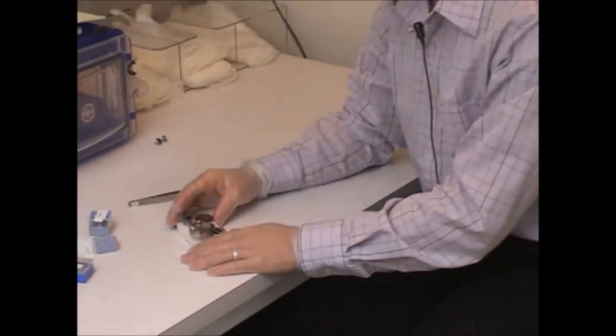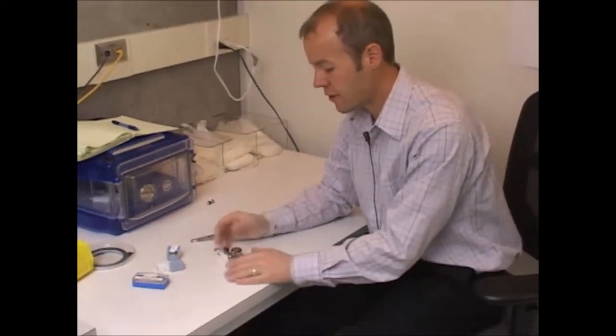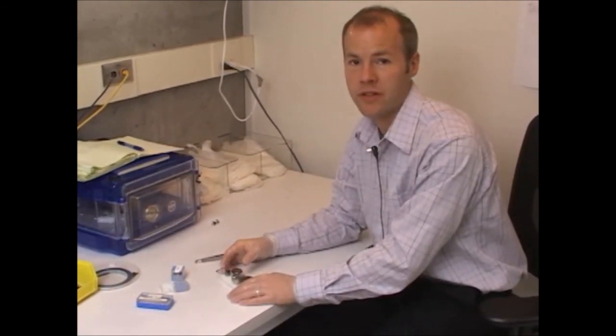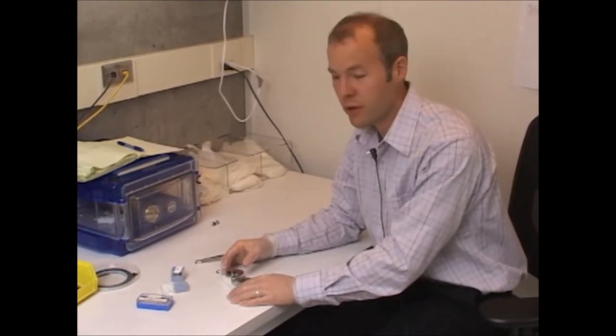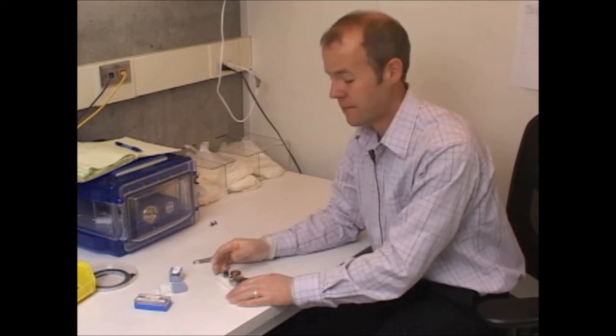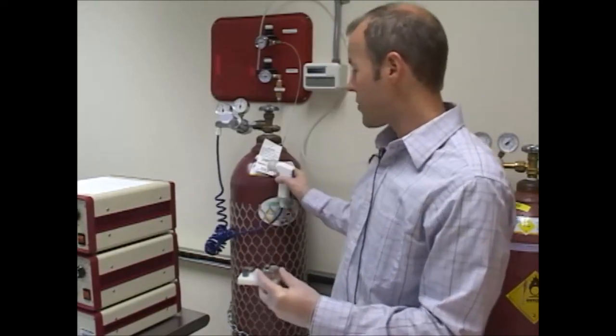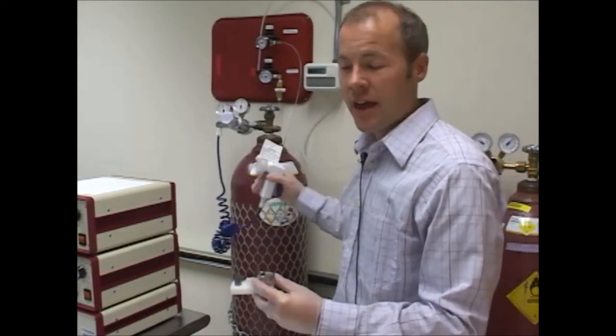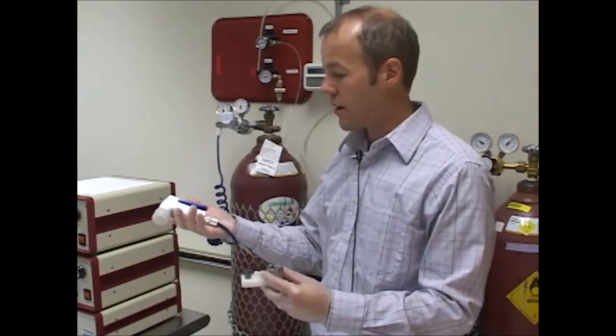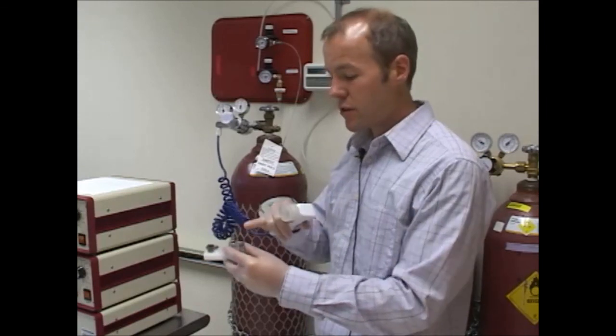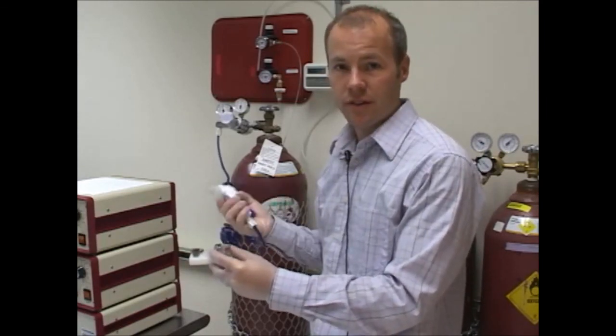They've both been kept dry in the desiccator. I've been gloved so I'm not depositing any material on them, and the next thing I'm going to do before I insert them in the chamber is just blow them lightly off with a stream of nitrogen gas to make sure that any dust that's settled on the surface is removed. So this is ultra high purity nitrogen gas, and it's fitted with a gas gun. So what I'm going to do is use a stream of nitrogen from this gas gun to just remove any loose debris from the surface of the sample before we image it.